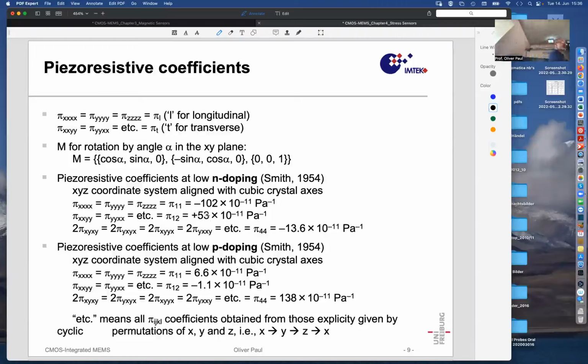But because they transform under a coordinate transform, we need to know for what coordinate system. And the coordinate system that it applies here is that of the cubic crystal axis. So people who measured these coefficients said, okay, the natural coordinate system is the crystal coordinates. I measure my sigma xx by measuring a resistor along that crystal coordinate under a longitudinal stress, and I call that coefficient pi xx because that's my x direction. And I will shorten this clumsy nomenclature by calling it pi 1, and it has the value of -102, and pi 1, 2 has the value of 53.